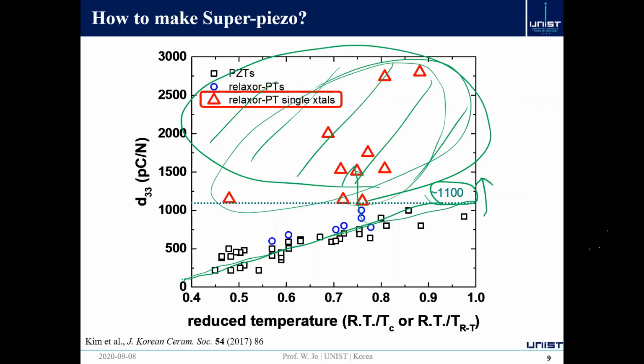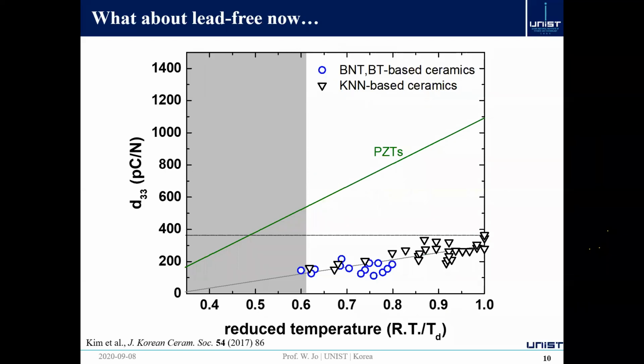And this is not all. We can also do another analysis on the lead-free piezoceramics we are interested in. So you remember this is the PZT line, which goes up to about 1100. I collected some of the accepted data on lead-free piezoceramics, and I plotted them in this reduced temperature scheme here, not the TC, but the reduced temperature.